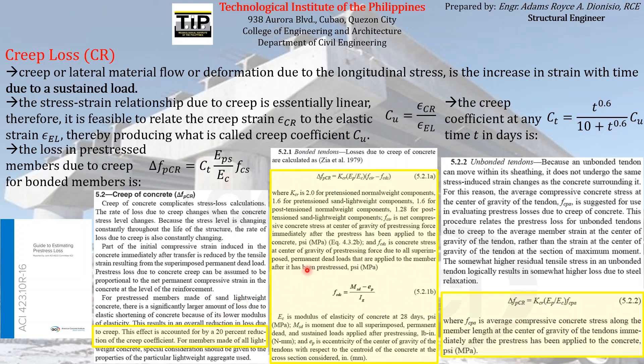This is the whole provision for finding the pre-stress loss due to creep for bonded tendons, and this is for unbonded tendons. You just have to keep in mind that if we are talking about pre-stressed members made of sand lightweight concrete, there must be a 20% reduction of the creep coefficient that we will use — which is KCR — if the concrete is lightweight concrete.